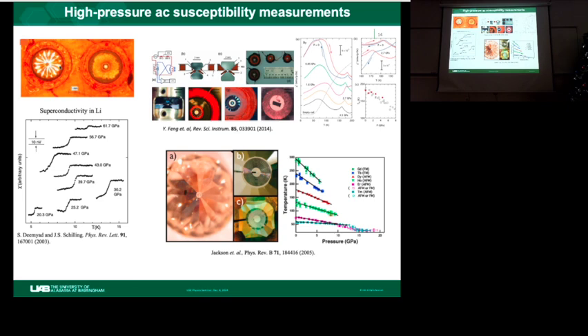Another technique we normally use in the diamond anvil cell is this miniature coil for AC susceptibility measurements. And you can come up with different types of designs. For example, here people got really creative and made a wedge shape instead of a cylindrical shape. You can also deposit or grow this coil onto the diamond anvil culet, and you have a much enhanced filling factor in this case. Here you have a tiny sample but a big coil, and you can actually measure with this coil, for example, superconductivity in lithium.